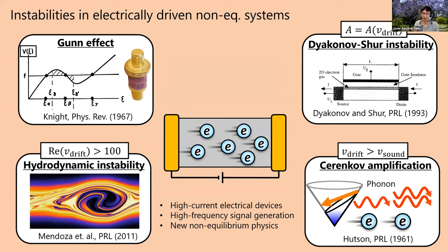One effect, which is very important, is the Gunn effect, which is an effect where if you take certain semiconductors and you drive them with a large electric field, they will actually spontaneously start generating high-frequency oscillations. It's called the Gunn effect, and it's due to a region where the material develops some negative differential resistance when you apply a large electric field. Don't have time to discuss it. It's a very interesting effect.